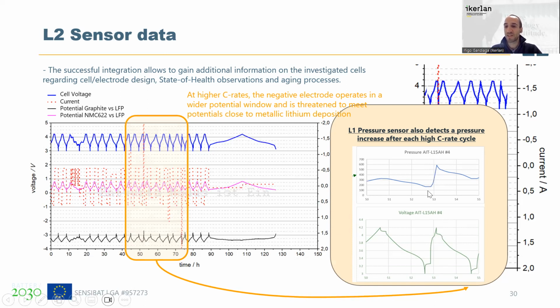For example, in a normal charge-discharge, we have an increase of pressure while we are charging the cell and a decrease while we are discharging it. But overall, the average pressure of the cell stays constant. Every time that we perform this 3C charge, this average jumps up, something like 50% more or so. So we not only have a reversible pressure increase, we also have a non-reversible part. This means that we are having some problems in the cell at these really high currents.